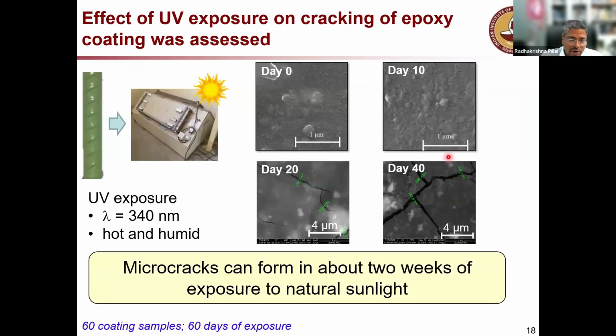Now, how long did it take? We did some study here. We found that within about 10 days, in the second picture here, there are a lot of cracks, micro cracks. When we expose this coating to UV radiation, we found a lot of crack formation in the coating. And that is not something good, because once you have a crack like this, then the moisture, oxygen, etc. can penetrate through this crack and reach the embedded steel surface and cause corrosion.